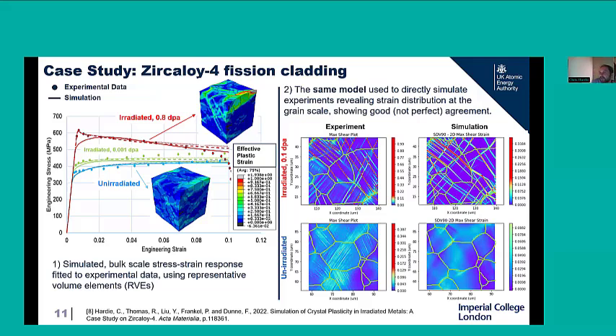And we can see that effect where the irradiation hardens the material, but it instantly softens after yield. And we could, to cut a very long story short, calibrate our crystal plasticity model with this representative volume element to represent what's seen experimentally there. And then taking that model with a single set of parameters and not changing it at all, we could directly simulate experiments, and this is on the right now.